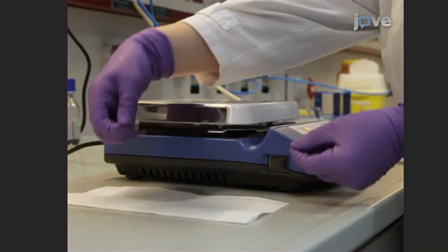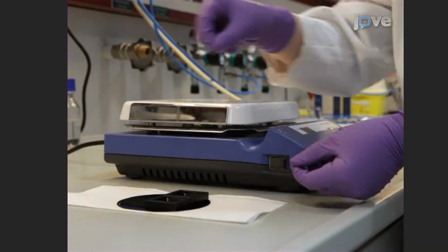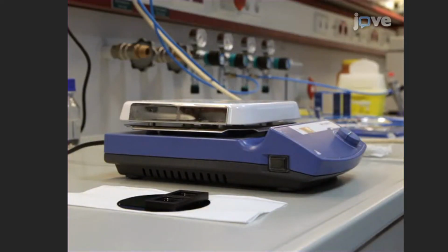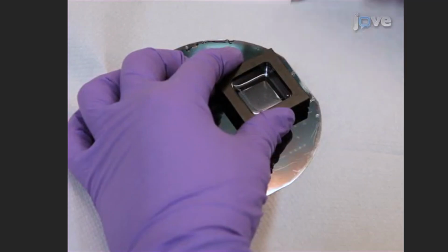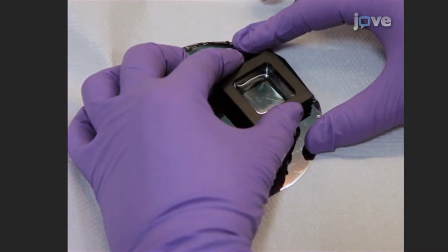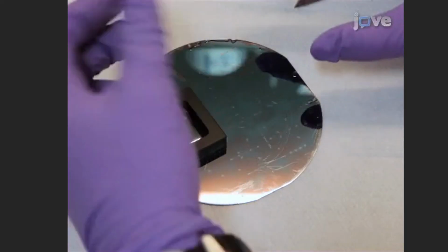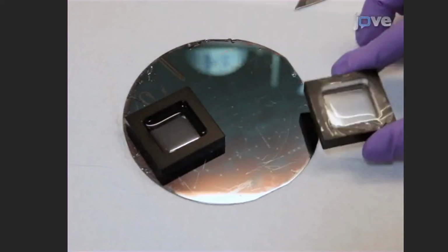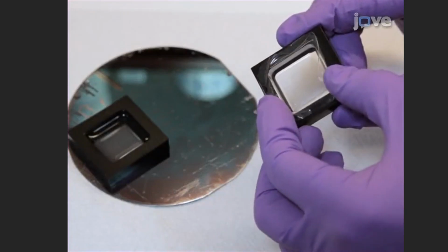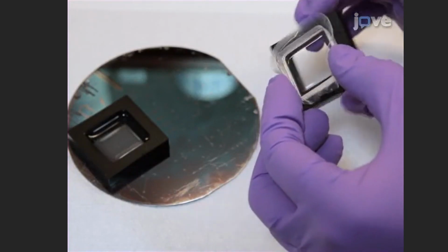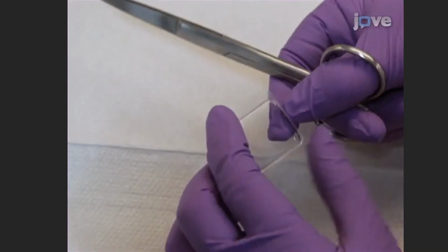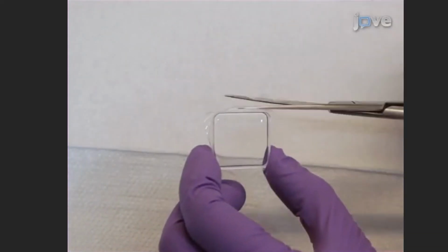Once cured, remove the wafer from the hot plate and allow it to cool on a flat surface. Afterward, while wearing protective eyewear, use a rigid scalpel to gently prise the frame and PDMS from the wafer from one corner. Remove the PDMS mold from the frame and use a pair of scissors to trim the device.